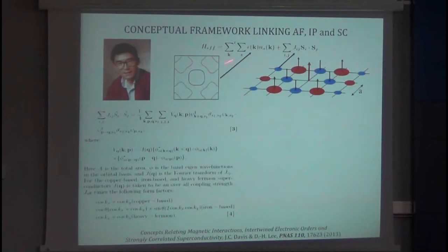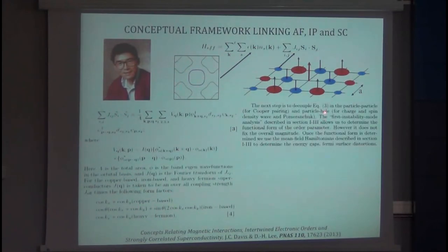Now you take these two pieces of information, Fermi surface and the strength of the magnetism, which comes from another source, usually neutron scattering, and you write them as a Hamiltonian in momentum space, taking the details of this magnetic interaction to be correct for the copper-based, the iron-based, and the heavy fermion superconductors. So this is not a model Hamiltonian for the magnetism. It's the known magnetism in these compounds. Then there's a process you can do where you can decouple this equation here for all the different order parameters which would be produced by this Hamiltonian.